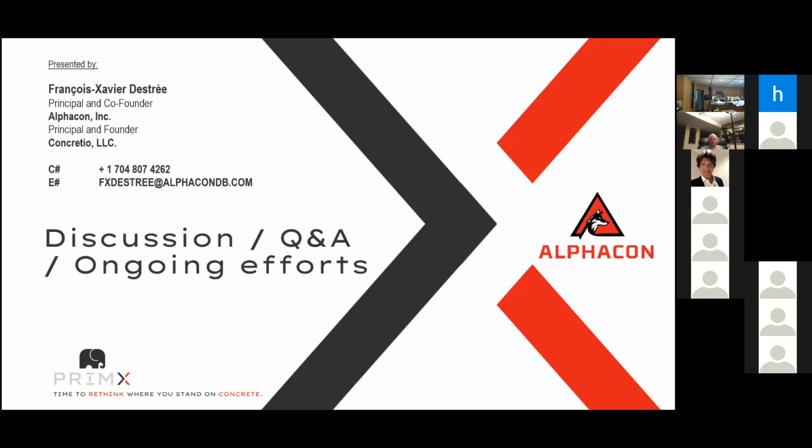Thank you, David. I can add that towards the beginning of the wet cure, you might have to add water. That is way less the case after, for example, the second week of the wet cure. You barely have to add on, provided you have a high quality wet cure material. That's often a one-time use wet cure that could be a double poly or a poly with an absorbent material below. Essentially, what you want to control is the interaction of that water with the ambience, because the drier your air, the more that water will have an affinity to go from liquid to water vapor, and that's where you have to add on.